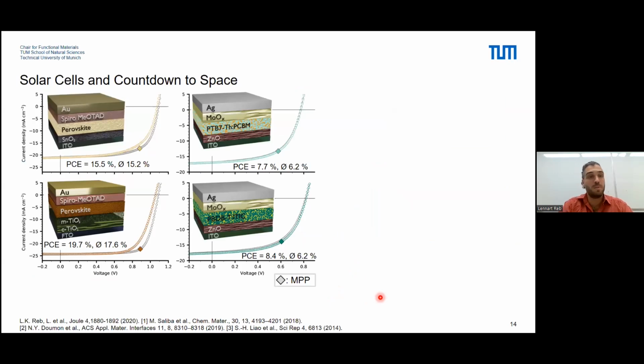The solar cells we used for this experiment are shown here. We have in total 4 different types of solar cells. On the left, you can see the perovskite ones. This is a classical MAFA perovskite. One is here in a mesoporous titania blocking layer architecture, and one is here with planar tin oxide.